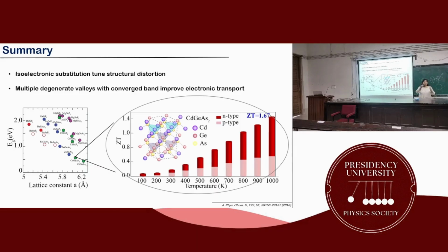Yes, that's what I was saying: with temperature, with any fluctuation, the chemical potential will change, right? But when you are doing a DFT or ground state calculation at zero Kelvin, DFT has this limitation. You cannot put in a temperature and do the calculation within DFT alone. So we find some way around. In my case, we stay under the rigid band approximation. You consider that with temperature, the electronic bands will not change drastically. This is true for most of the materials that we work with. And then you change the Fermi energy to understand the chemical potential.